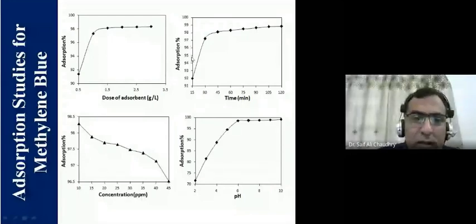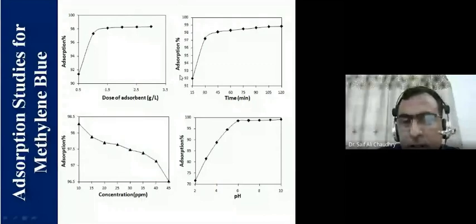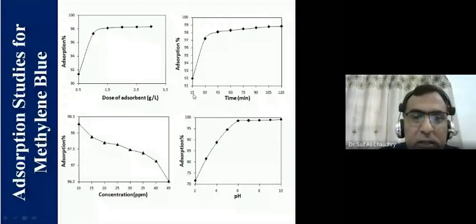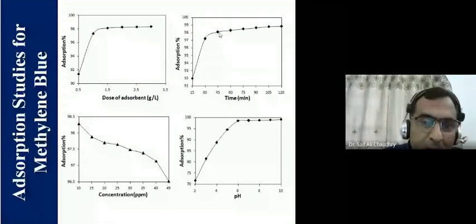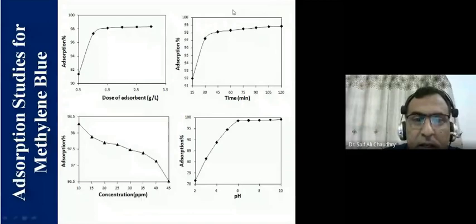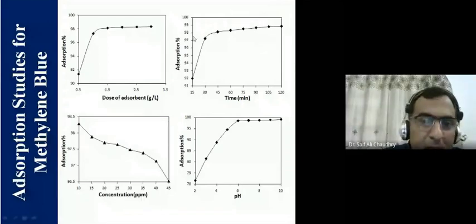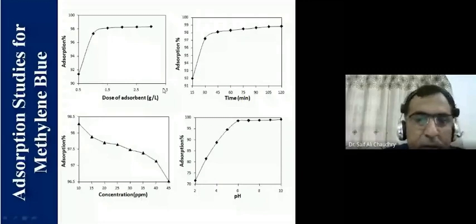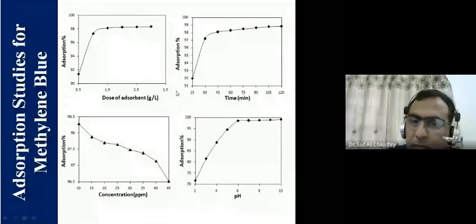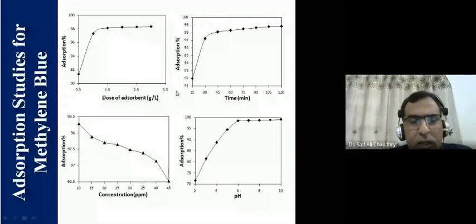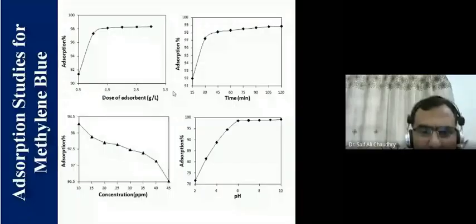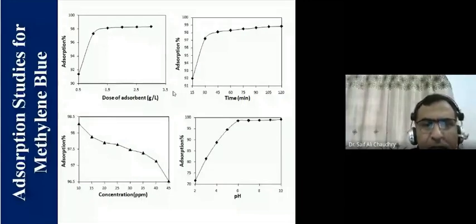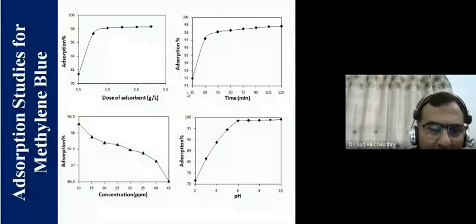Just a plot between adsorption percentage and time. Initially we started with a 15-minute duration, and it reached 45 minutes. So 45 minutes is sufficient time for the cleaning of around 97 or 98% of the methylene blue dye we have taken. So this time is a very good duration. It is not so long a time, therefore we can apply this material on commercial scale also. And this is something which is required.